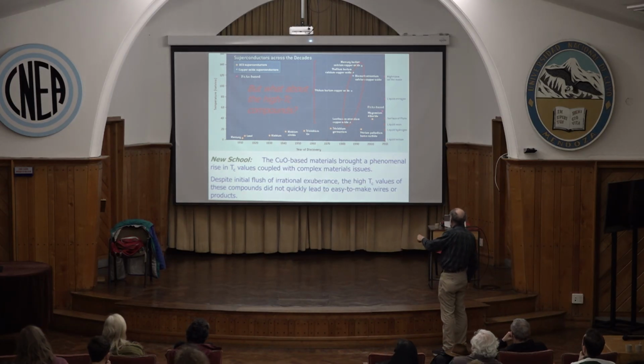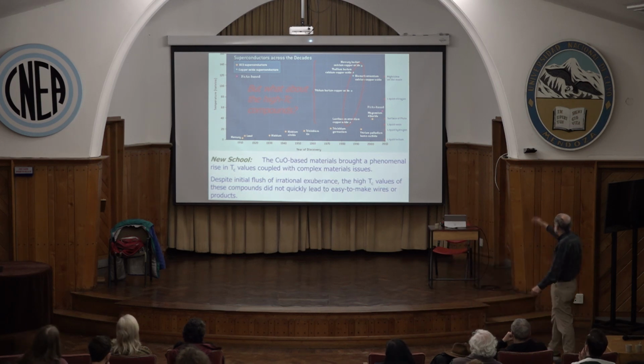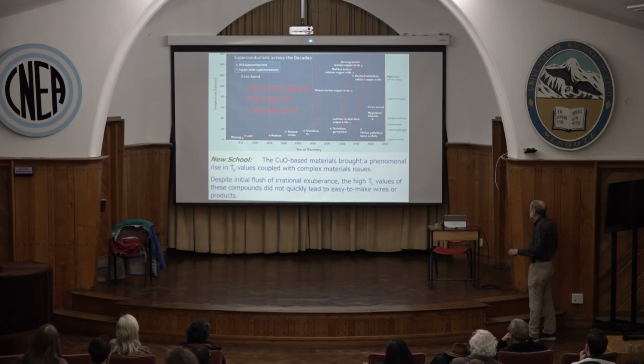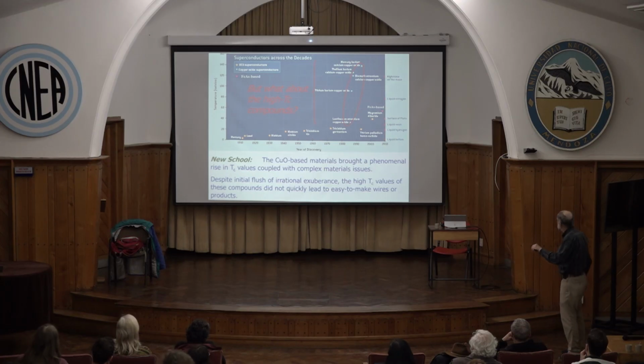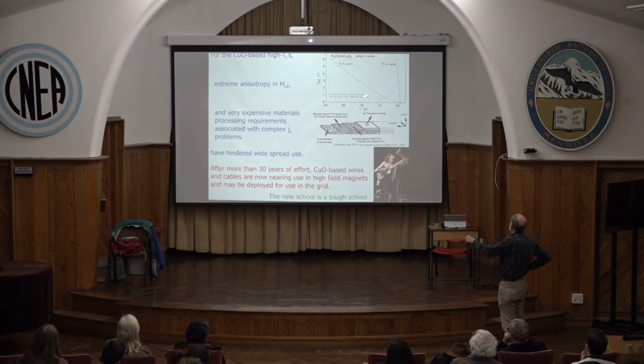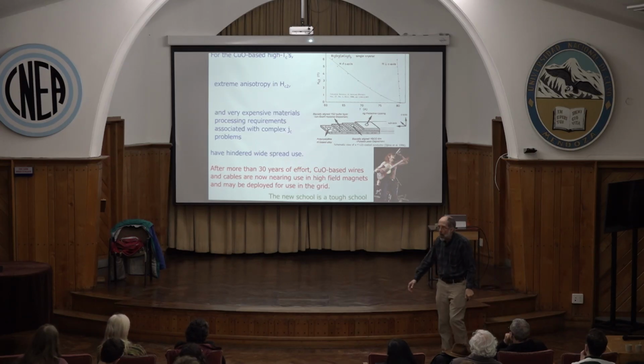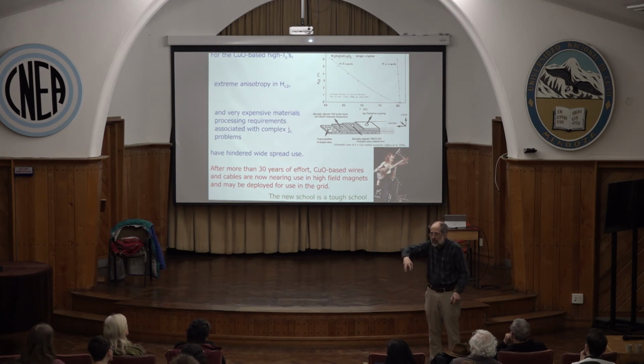So we can start with the cuprates. Copper oxide-based materials have a phenomenal increase in TC, but to paraphrase Alan Greenspan, despite the initial flush of irrational exuberance, it has been a long hike to make these into wires that work. Okay? And one of the reasons is they're highly anisotropic for their HC2, but the more profound reason is, given that this is a special type of superconductivity, if you have a kilometer-long wire, which you need if you wind coils or have power, every polycrystalline grain of the superconductor has to be oriented within a few degrees of each other, over the whole kilometer. That's not easy. And it's taken decades to figure out ways of making this so it works.